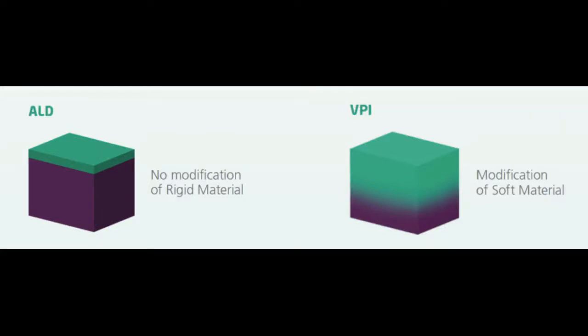VPI, also known as SIS or sequential infiltration synthesis, is derived from an ALD process with cyclical exposures of precursors, but the substrate is often soft, allowing deliberately longer chemical exposures to facilitate diffusion into the material and creates a hybrid material rather than creating hard interfaces and conformal films.